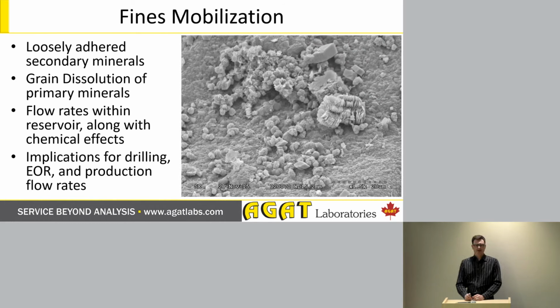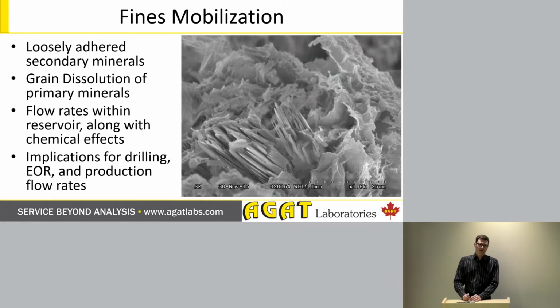Another example here is kaolinite. This is kaolinite booklets that are loosely adhered to the surface of a quartz grain. And again, if you start to increase your flow rate, in combination with chemical changes as well, which might actually precipitate them breaking off and starting to flow, we could well have serious implications for our drilling, enhanced oil recovery, and production flow rates.